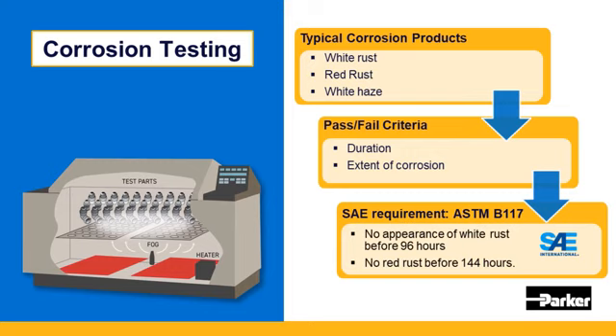Though different end users may develop their own requirements, all those criteria are based on how long the part is in the test and the extent of corrosion of the plating after the test. For example, SAE International, the governing body of hydraulic tube fittings and adapters, published the minimum protection requirement in accordance with the neutral salt spray test: no appearance of plating corrosion before 96 hours and no appearance of substrate metal corrosion before 144 hours.